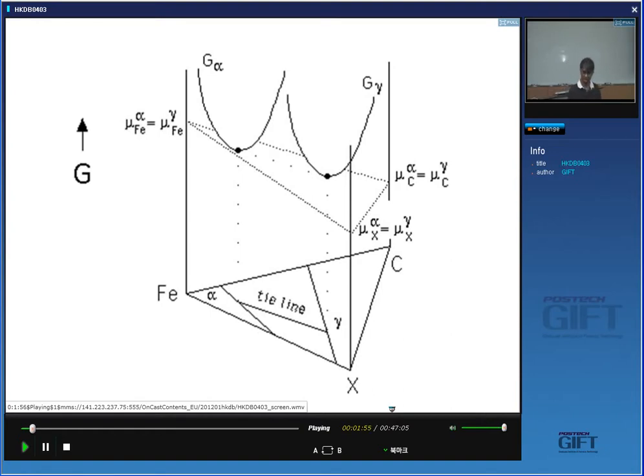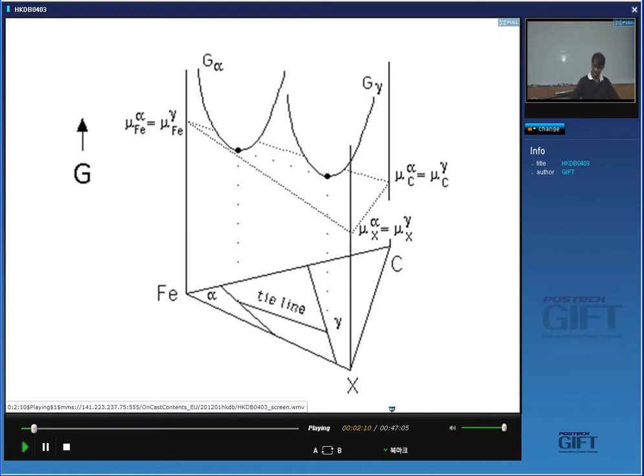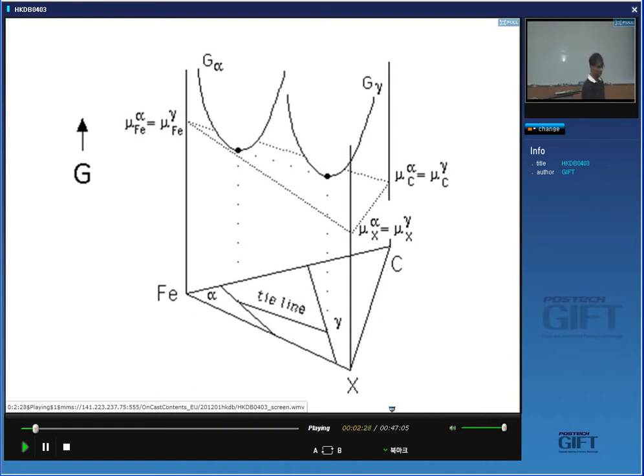Just like a common tangent construction, but now we have a plane touching two surfaces, and the projection of these points onto the graph gives us the tie line. But we have the additional freedom that I can get a whole set of points which remain in contact with the tangent plane if I rock that tangent plane. So I can generate an infinite set of tie lines on this iron-carbon-X plot, which defines my alpha plus gamma phase field at a constant pressure. So I can have many combinations of ferrite and austenite which are in equilibrium with each other, because I've got an extra degree of freedom by adding manganese to the system.